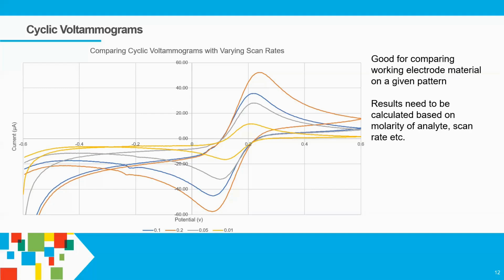It's very good if you have a design and you want to match a carbon ink that you've already got to something else, trying to get the best candidate to match it. If you're a startup starting from scratch, or a PhD student trying to make a biosensor from scratch, this doesn't really tell you much information. It tells you whether the mediator in a system is reversible, and it also tells you the peak-to-peak separation. But this also changes depending on the actual design, whether it's a 3-electrode system, a 2-electrode system, all sorts of things.